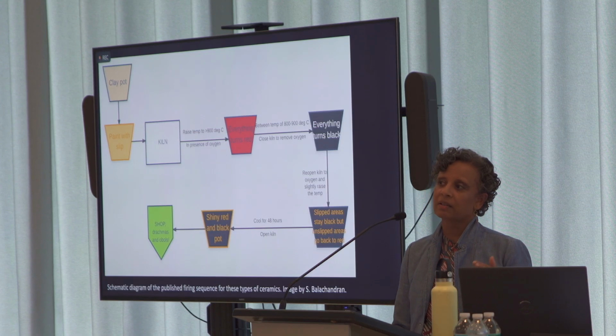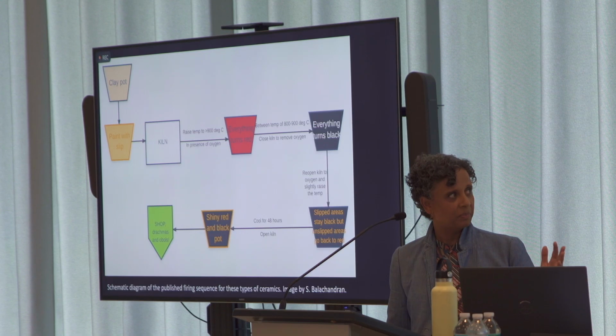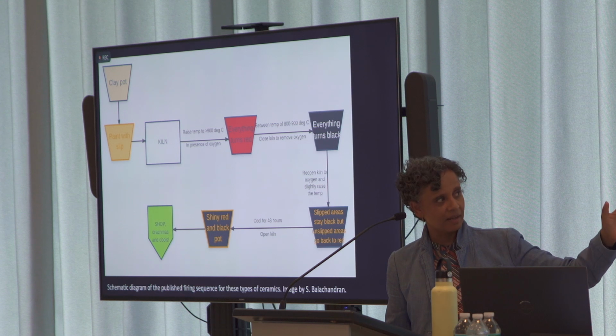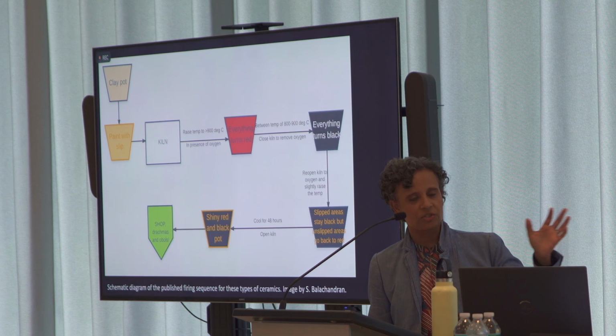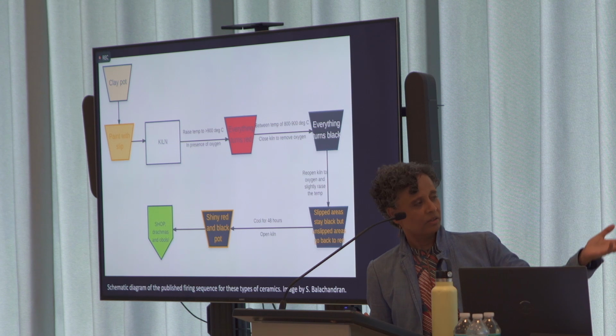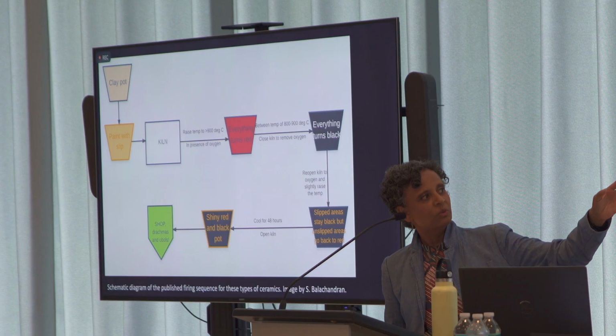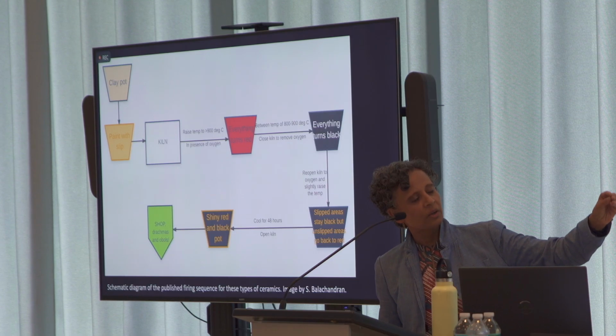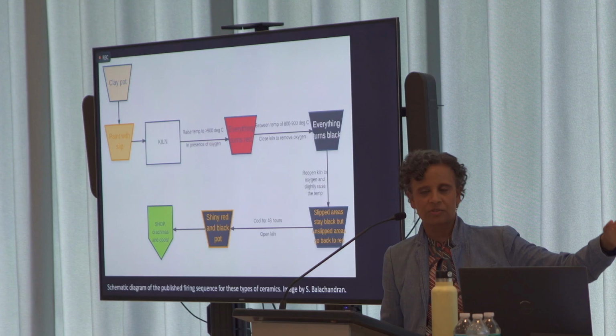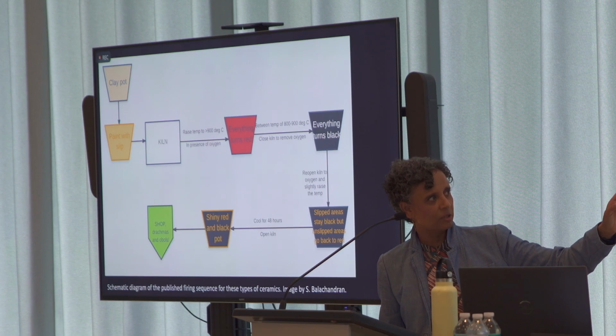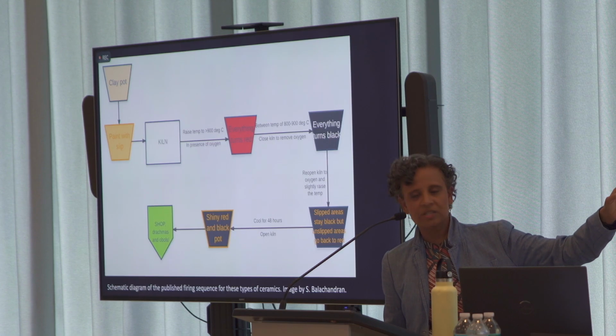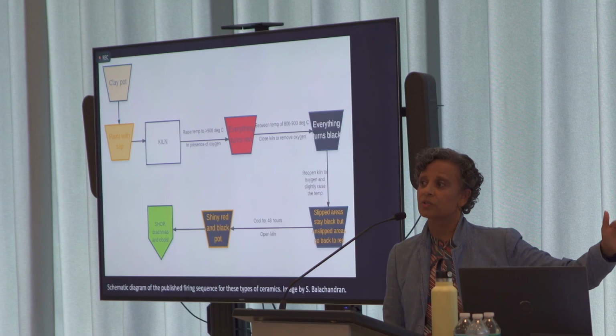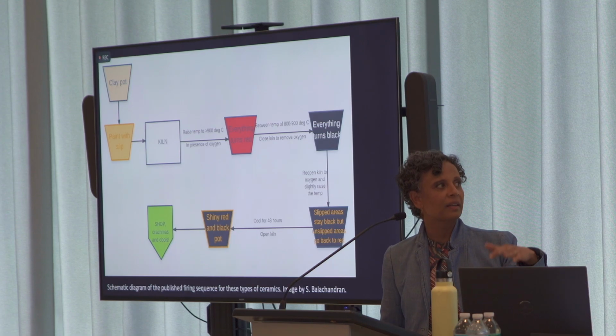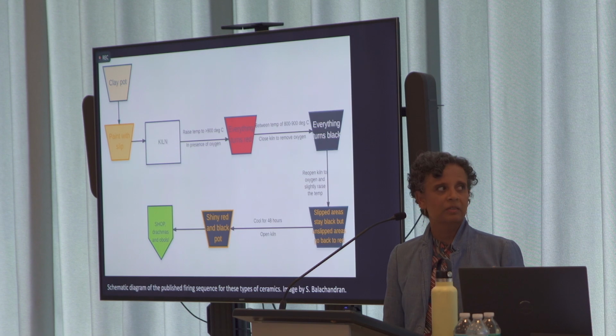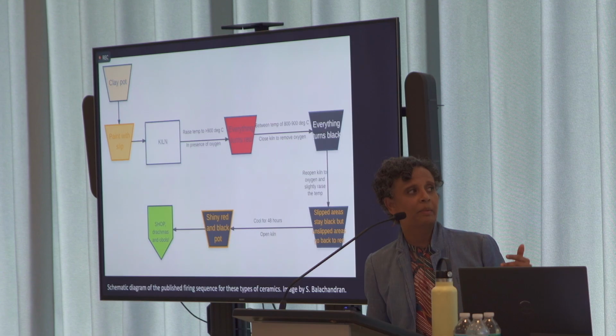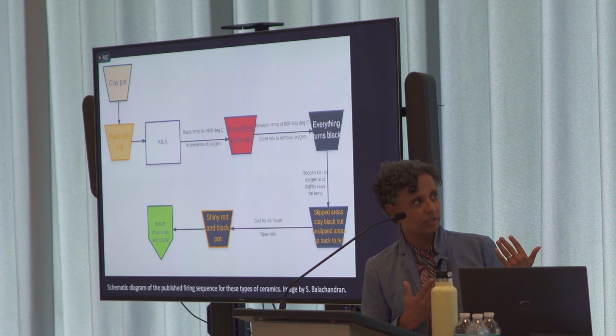At this point, everything on your pot is going to be red because the iron oxides on the pot, because of the presence of oxygen, create these red iron compounds. Then you lower the temperature, or excuse me, you close the kiln somewhere between 800 and 900 degrees centigrade. That was his number. And you close it to remove oxygen and everything turns black. And at this point, everything that is reacting inside the kiln is turning into these black iron compounds because you no longer have oxygen circulating.